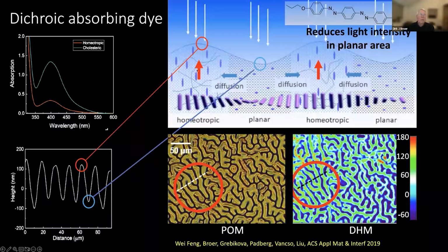So here we see an example. This is the example where we are using the dichroic absorbing dye in this case. And what you will see is that indeed the perpendicular areas become high and the planar areas become low. We could easily demonstrate this by comparing our polarizing optical microscope pictures, where we can determine the location of the planar areas and the perpendicular areas, with our digital holographic microscopy images, where we get an impression of the heights of these structures.